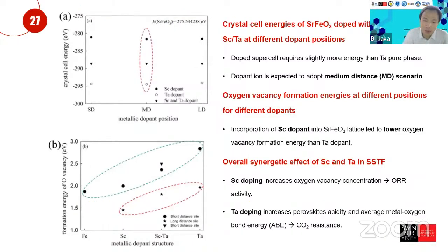Then I think the slide in here is basically just showing the explanation as to why, when you dope scandium with the tantalum, you get a much better performance than if you only dope with one dopant, either the scandium or the tantalum. Basically, they do density functional theory calculations. As you can see in here, the crystal cell energy, if you put in the two dopants, is in between. Okay, but the formation energy of oxygen vacancies will be a bit different. So the Sc doping is basically increasing the oxygen vacancy concentrations, and the Ta doping is increasing the perovskite acidity and average metal-oxygen bond energy, which is contributing to a better CO2 resistance.